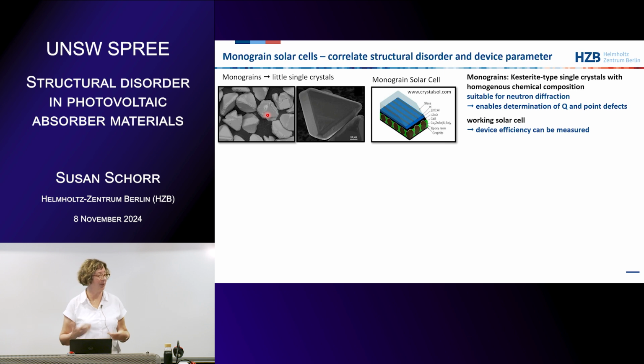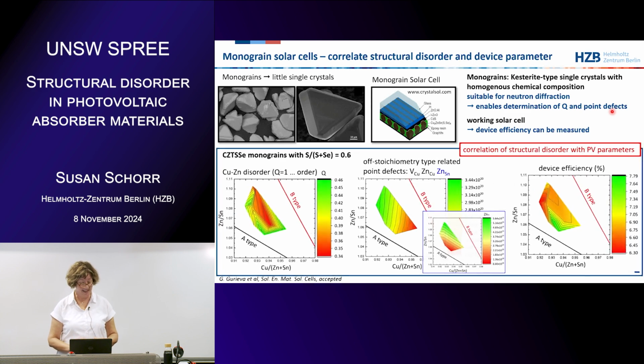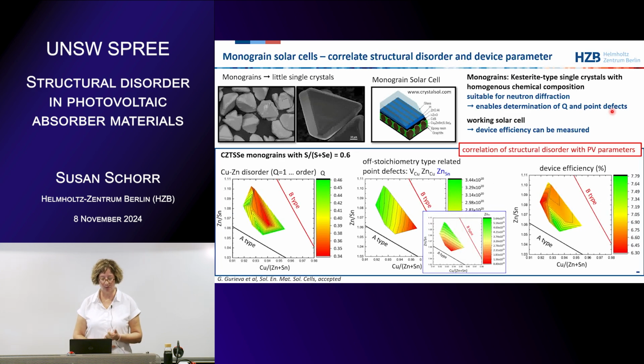And because it's like a powder, we can do our neutron diffraction experiments on that and determine the order parameter and the point defects. And then we can compare these values with the real device efficiency and the VOC and other parameters, because it's a working solar cell later on. This is just an overview of copper zinc tin sulfide selenide monograins with a sulfur content of 60%, where they are all in between the A and the B type line.